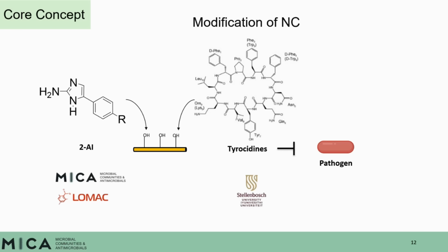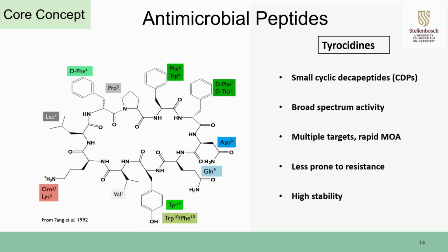Because nanocellulose itself does not have an antimicrobial activity, we modify the nanocellulose either with Tyrocidines developed by Stellenbosch University or with the 2AI compound developed at our lab, the MiCA lab, in collaboration with KU Leuven, and see how they inhibit potential pathogens. We start with the Tyrocidines, which are a class of small cyclic antimicrobial peptides isolated from soil bacteria. They have a broad spectrum activity and multiple targets, and they have a rapid mode of action, which makes them less prone to resistance and highly stable. That's why they are great candidates for our coatings.